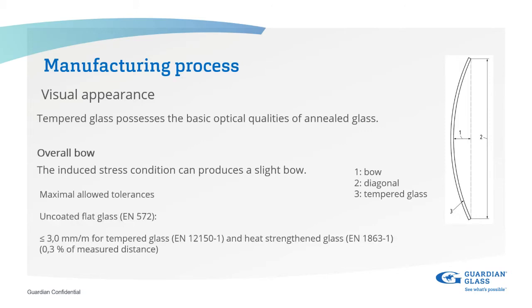So the maximum allowed tolerances for uncoated flat glass, EN 572 stipulates 3 mm per meter for tempered glass. That's to EN 12150, and also for EN 1863, and for 0.3% of the measured distance.